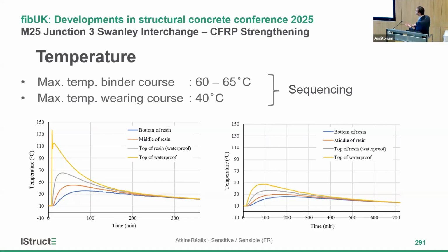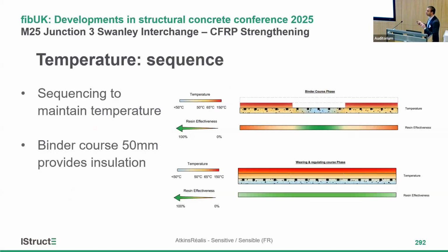Because when the binder course is applied and the temperature does reach 65 degrees, there is a short period of time, roughly close to 20 minutes, where the resin is not effective. When the resin reaches the glass transition temperature, it becomes more like a rubbery thing and is not effective in carrying the load. So the solution was to apply the binder course in sequence. So at least we have the minimum load carrying capacity on the bridge